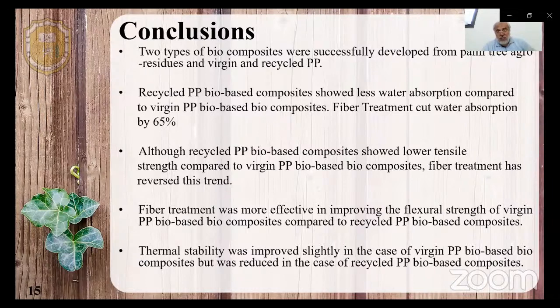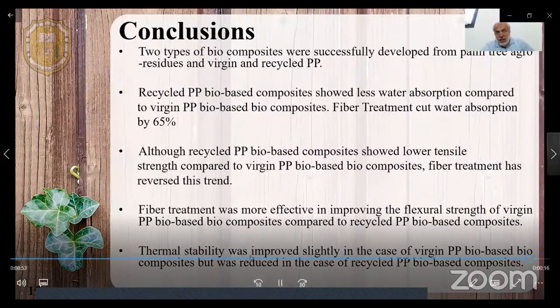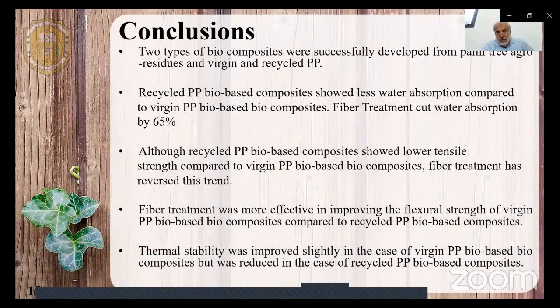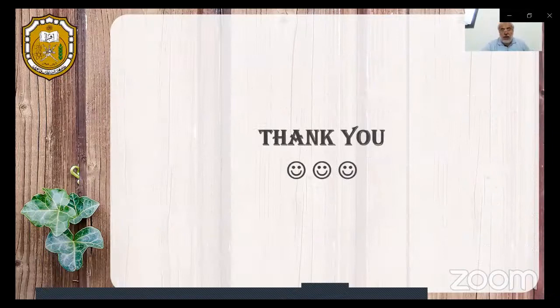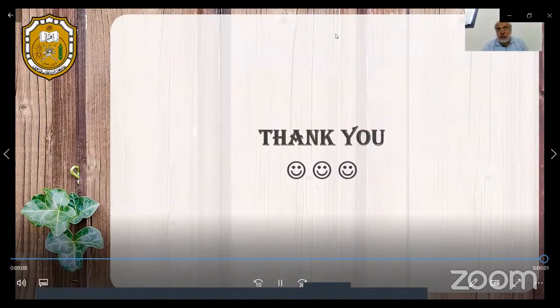Fiber treatment was more effective in improving the flexural strength of virgin PP bio-based composite compared to the recycled PP bio-based composites. And thermal stability was improved slightly in the case of the virgin PP bio-based composite, but was reduced in the case of the recycled PP bio-based composites. That's my presentation, and thank you for your listening.